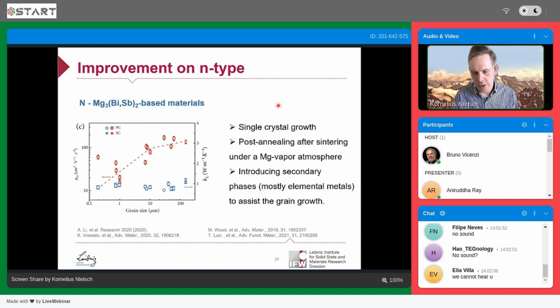We also looked later on at how to further improve this thermoelectric device, especially the material from the material point of view. One of the specific characteristics of the magnesium-antimony based materials is that you need rather large crystal size. For bismuth telluride, you can produce rather small crystals, and that even improves the thermoelectric performance by keeping nearly the same electronic properties, while significantly reducing the thermal conductivity. Whereas in the magnesium-antimony based compounds, you need rather large crystals, ideally single crystal, but this is too expensive.